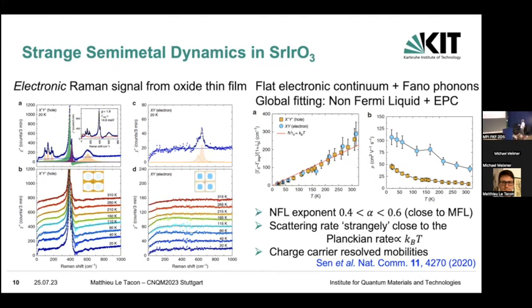Something which was also quite interesting is that from this we can get some kind of charge carrier mobility. So we can see that the electrons are essentially more mobile than the holes, which is something that you can also see in the Hall effect, which is dominated by the electron charge carriers.